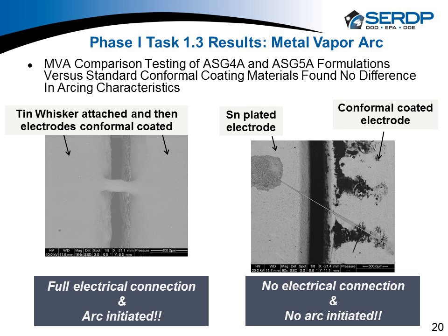One of the things that the SERDP project allowed that we did not see in the industry, which will seem kind of silly, but we wanted to confirm the obvious. So what you see here on the right side is the guys at the University of Maryland, Dr. Mike Osterman. Here's the electrodes, and I talked about how we would bridge an electrode or a whisker across the electrodes. So this electrode has no coating on it, and they use conductive silver adhesive to bond a whisker to it. On the right side of this electrode, we put acrylic or parylene or the ASG coatings on. And then you bring the electrodes in contact, so this whisker is now making contact with this side of the electrode. So when Mike applied 50 volts, if it could conduct, it would go from this electrode through the whisker to this electrode. We never had any electrical connections.